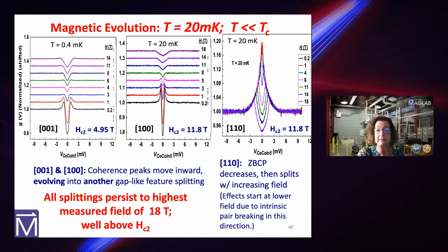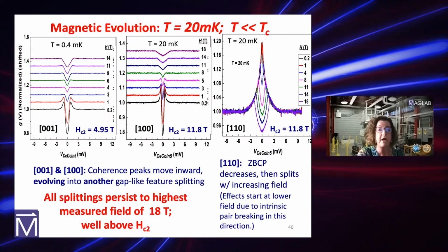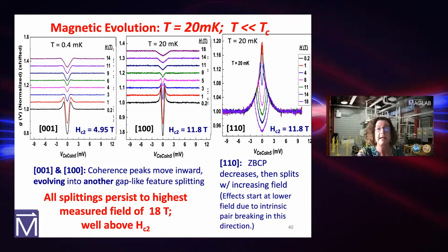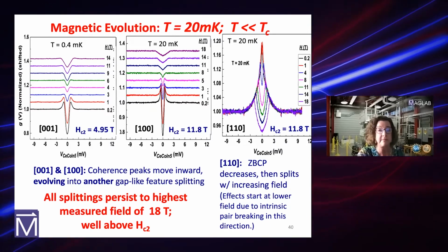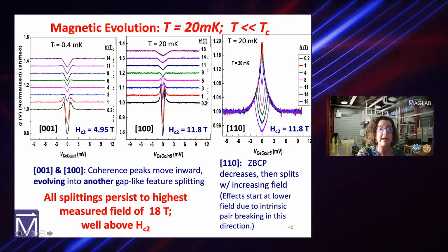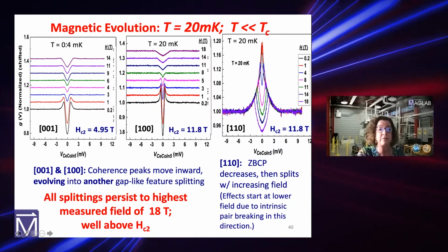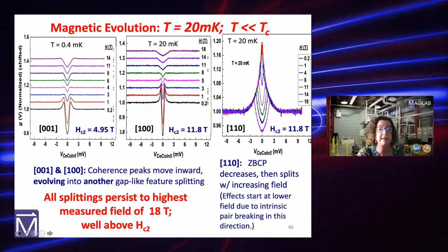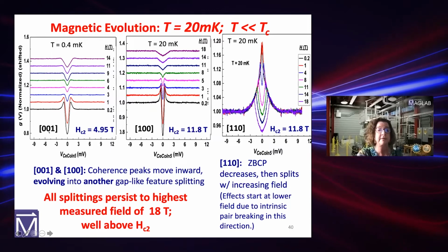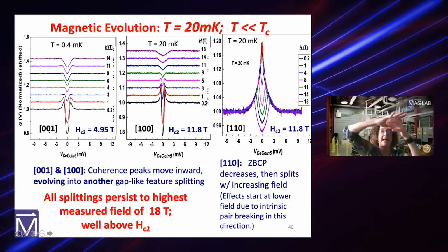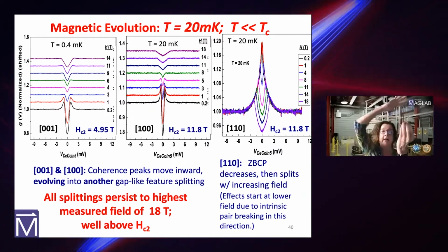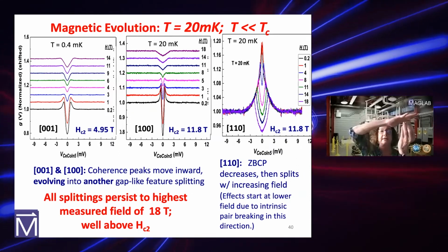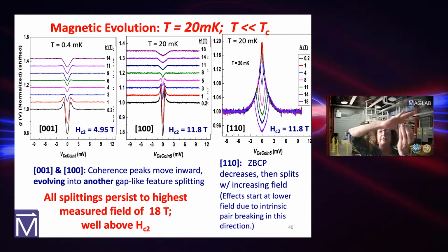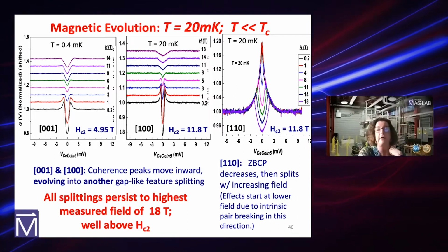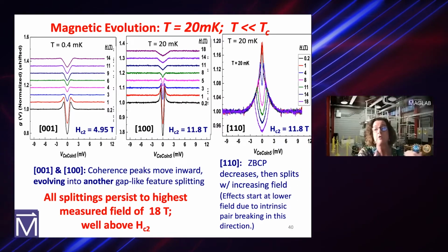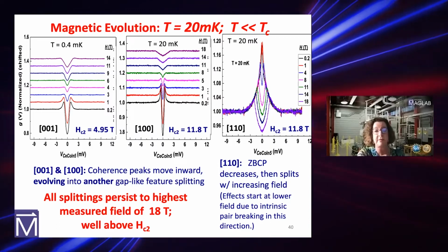That's a little detail here. Now I want to talk about the magnetic evolution. And in the magnetic evolution, we are now all at low temperature. Here, this one, in this orientation, 001 and 100. So the 001 is coming down on the C-axis. The 100 is coming in like in the A-axis. And we can mount these and polish them down. And then this is the 110, of course, is the nodal direction for a dx squared minus y squared superconductor.